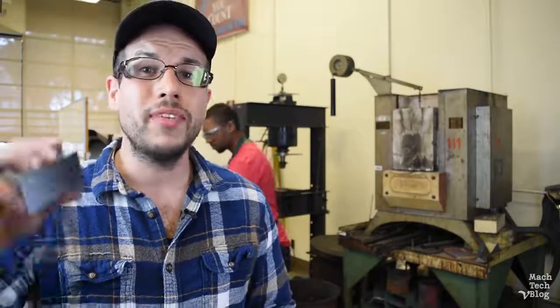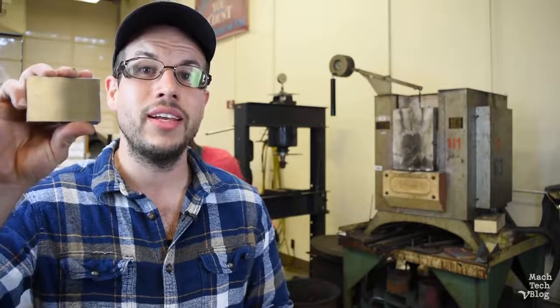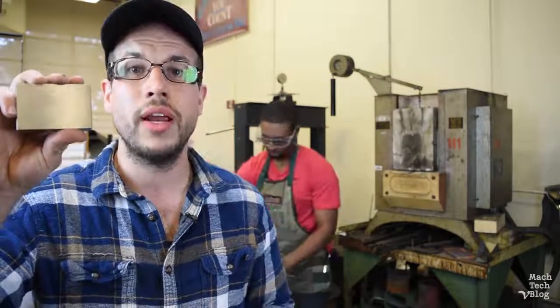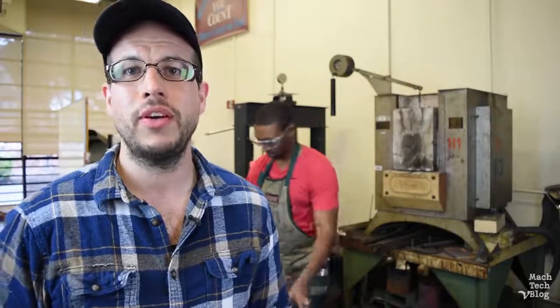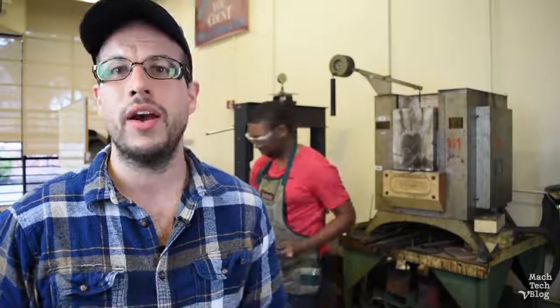Since they're going to be used as tools, it's common to heat treat them to harden them so that they're more wear resistant. But the problem is that these are made out of 1018 steel, which is a low carbon grade. It's a good general purpose steel, but it doesn't have enough carbon content to really heat treat and harden properly in the furnace. The solution, of course, is to add more carbon.